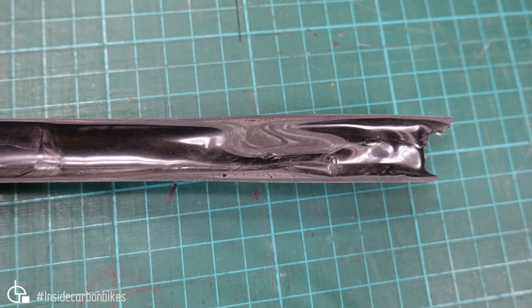And here you can see, that's the back end, so the other side of the cut piece, and you can clearly see the wrinkling going on here, where the fiber's going all the way around like that, when ideally you'd want the fiber just going across like that. Also some porosity in the root, and then porosity. It looks like some sort of syntactic filler through here, and you can see there's porosity in that. So not the cleanest area, but again unlikely that that's going to be causing any significant problems in the long term. I mean, you could get a crack indication popping up through that over time, just because of that wrinkle.